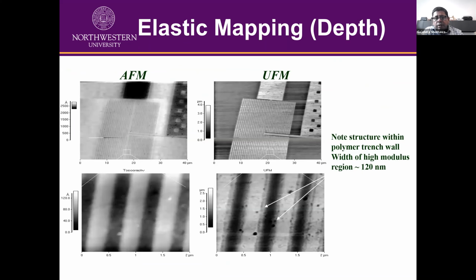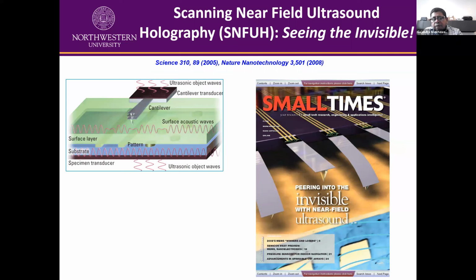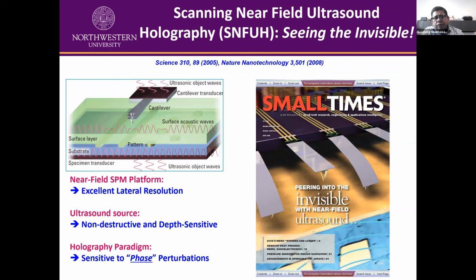Then you can see the examples of metal interconnects where you see the metal lines. The softer region appears as a darker contrast in these images, and the brighter contrast in the topography, which is a stiffer material, appears as a darker contrast. So you can see on the bottom right image, you can even see clearly the sidewalls and the CMP polishing effects in these metal interconnect lines. All these black spots are basically the effect of CMP polishing. So you can see the change in the mechanical properties at the edges when you do the CMP process on these metal interconnects.